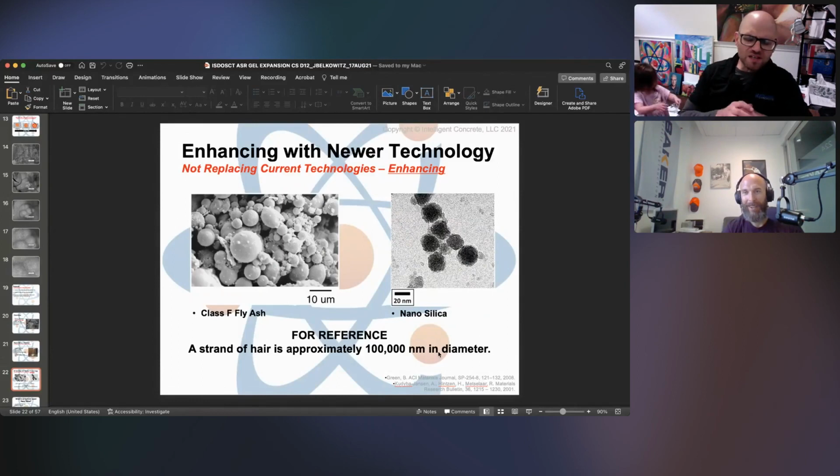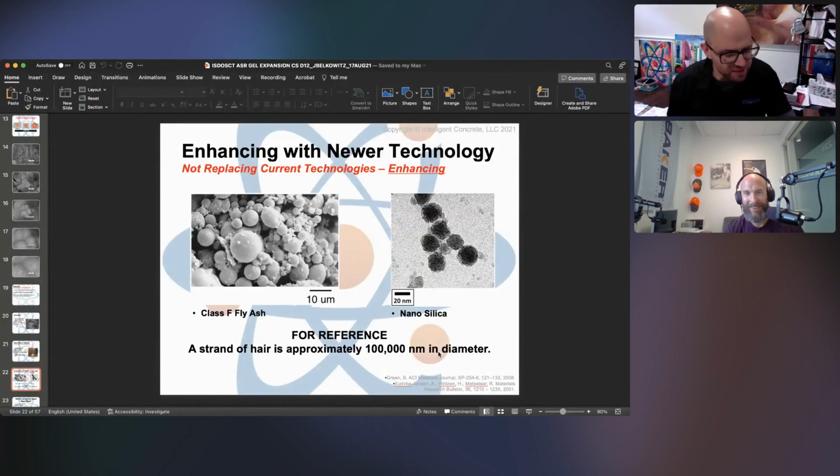So the other way is getting some type of monomer, or some type of basic solution that incorporates a silicate. Normally we have potassium silicate, a sodium silicate that we put in solution with an acid. We rip and strip off the salt. And what happens is the silica just starts stacking up on each other and growing into these different shapes. The bigger it gets, the shape changes.